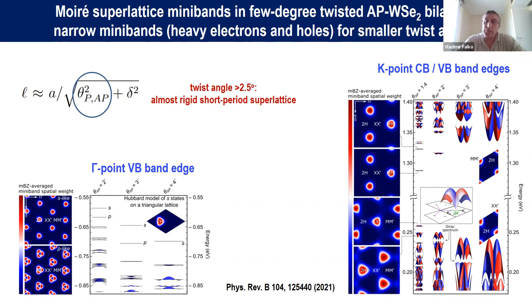And then the linear scale separation in terms of distances between those quantum dots, which follows the decreasing angle of misalignment through the longer period of the Moiré superlattice, makes the bands narrower and just transforms the system into arrays of quantum dots from what otherwise we would describe as a quantum material with mini bands.